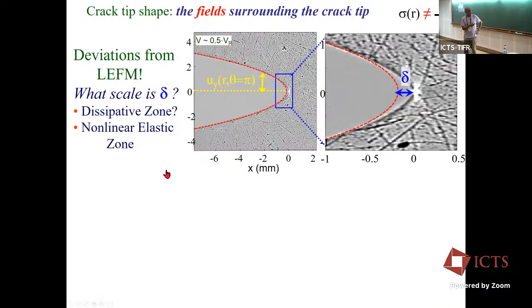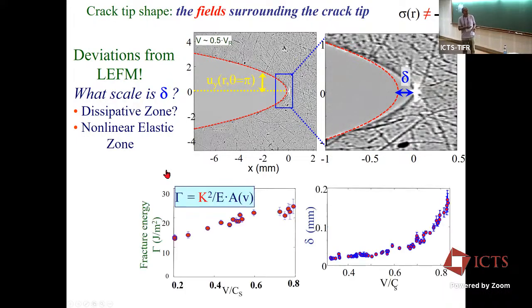Now, what is this scale? Is this the scale of dissipation? We thought, okay, we're looking now at how nature is blunting the stress singularity here. Or could it possibly be a nonlinear elastic scale? Why nonlinear elastic? Because we're pulling the material so hard that linear elasticity can't hold anymore. So how can we check? We just looked at the dependence of this scale on the crack velocity. This scale is a very highly nonlinear function of the crack velocity. It gets larger and larger the closer you go to the asymptotic velocity. At the same time, we measure K by just this parabola. Using each snapshot, we can measure the fracture energy or the dissipation, and it's fairly well behaved.